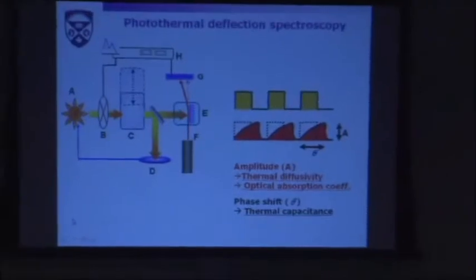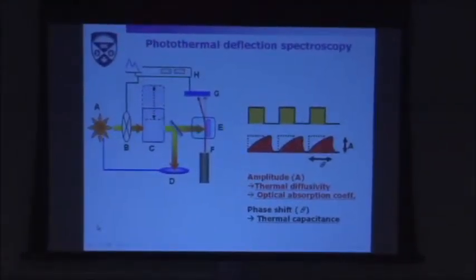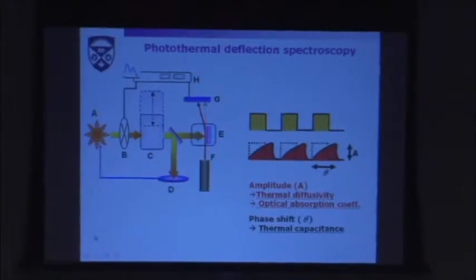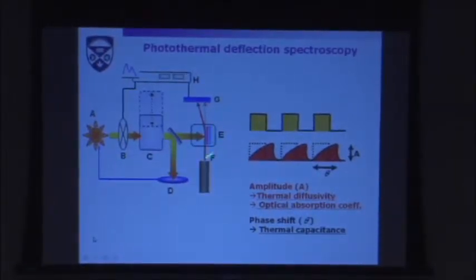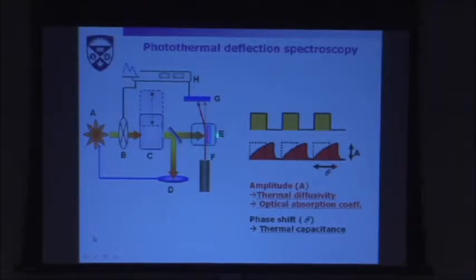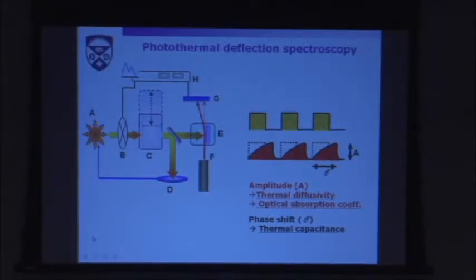And therefore, if I am illuminating a film with pulsed light, like I'm chopping light, I have pulses, boom, boom, of light that heat up a film in a photothermal fluid, in this cell here. Locally here I have a lensing effect, a gradient in density of the photothermal fluid. Can be air, but air is not a great photothermal fluid. It's a relatively poor photothermal fluid. There are fluids that are much more photothermal, like carbon tetrachloride. There are even photothermal fluids that are produced by companies.